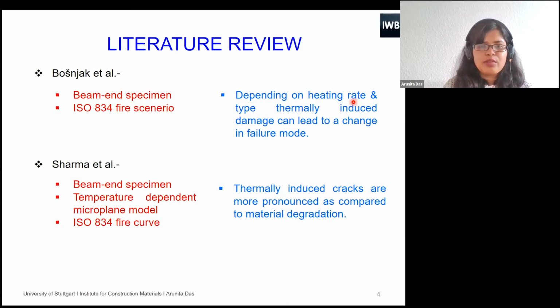Recently, my colleagues Dr. Bošnjak and Dr. Sharma have shown that using beam end test specimens and a realistic fire scenario, the degradation of bond is really huge, and the heating rate and type have a very huge impact on the results of bond reduction. So the study which I will show here is a step forward from the study which my colleagues have done, but I will be considering several other parameters, numerical as well as experimental, and at the end of my PhD thesis, I would like to present a model so that in future people can calculate the residual bond capacity after fire.